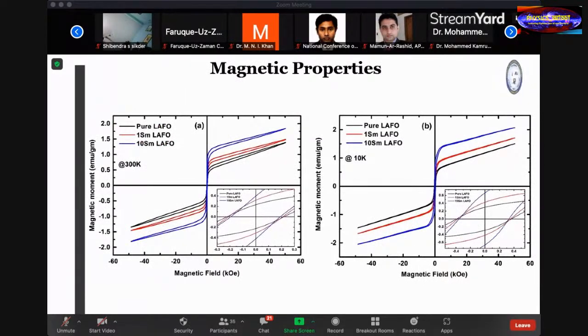These are the magnetic properties. We can see that with the increase of the doping concentration, magnetization was increasing, and from the inset we can see that remnant magnetization was increasing with the doping concentration. This is for the 300 Kelvin result, and magnetization at 10 Kelvin gives us the same result.